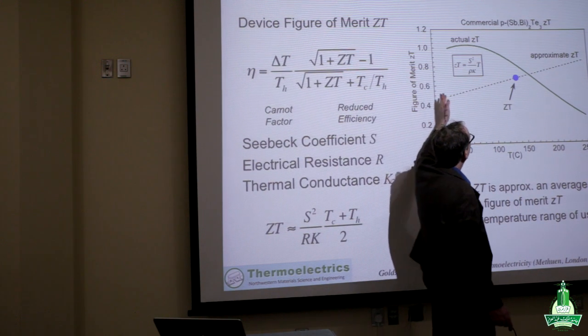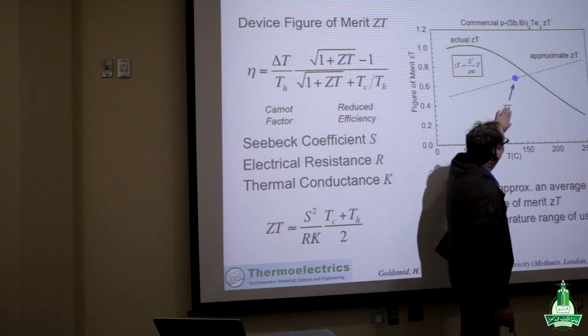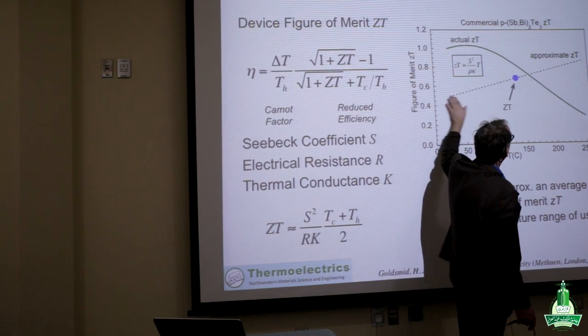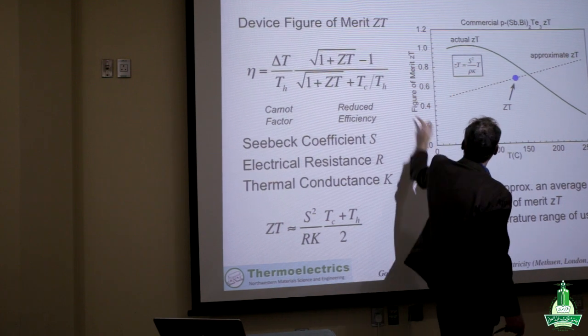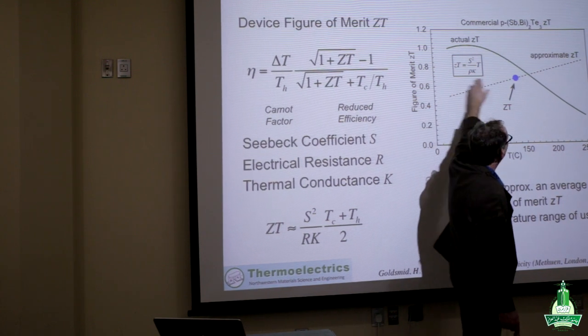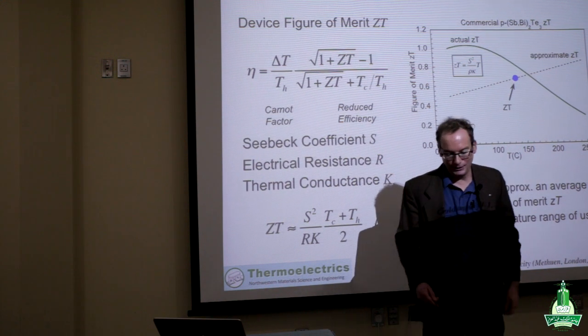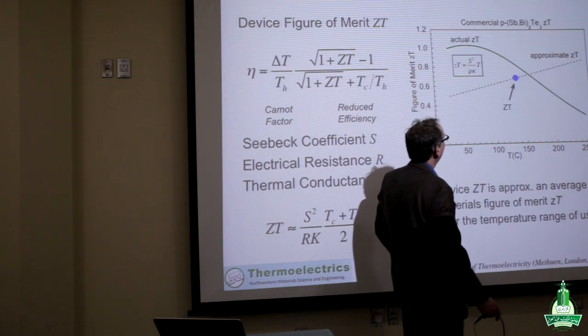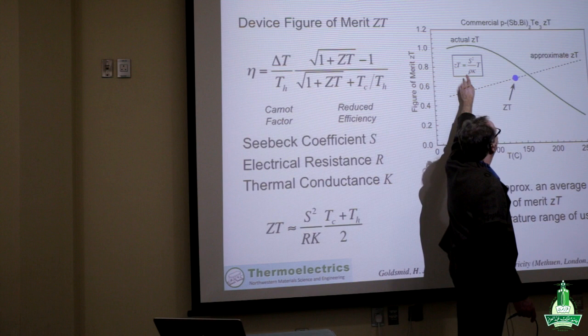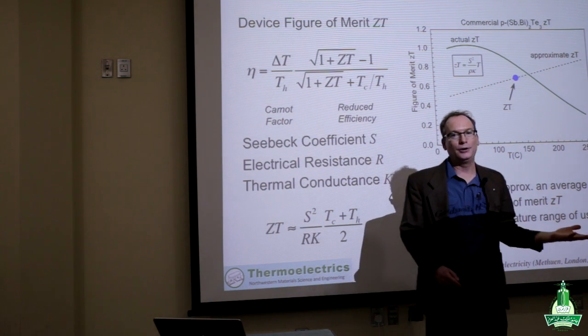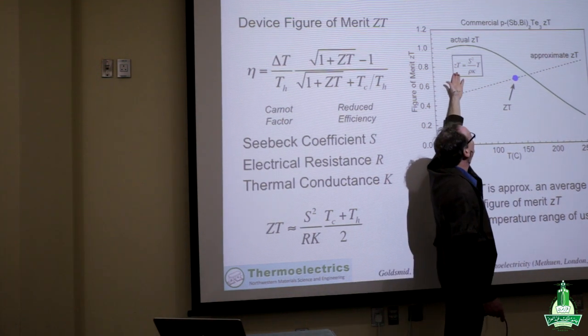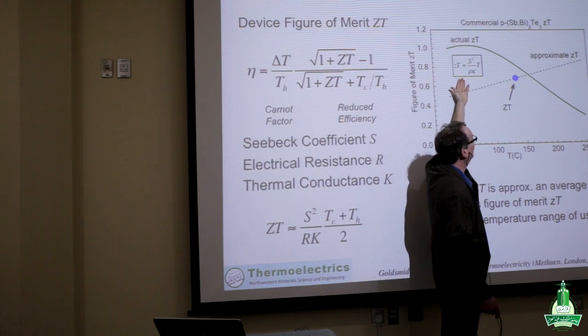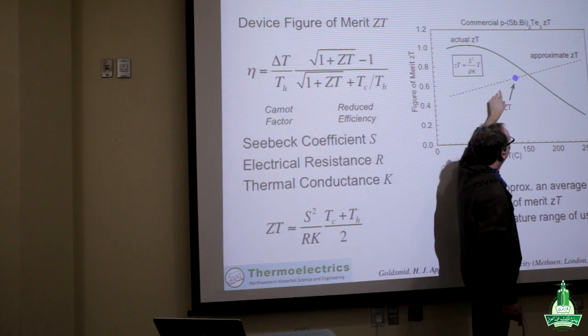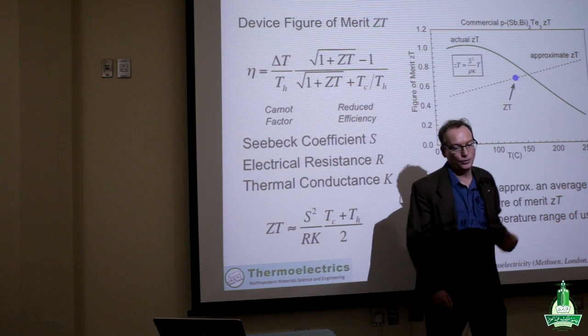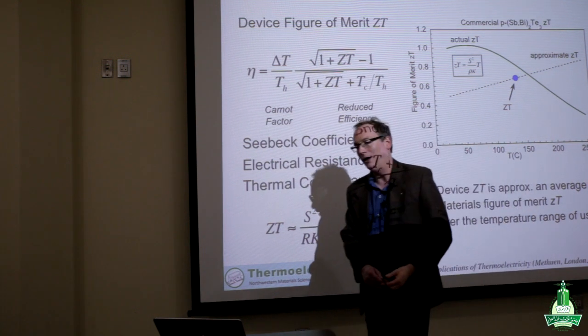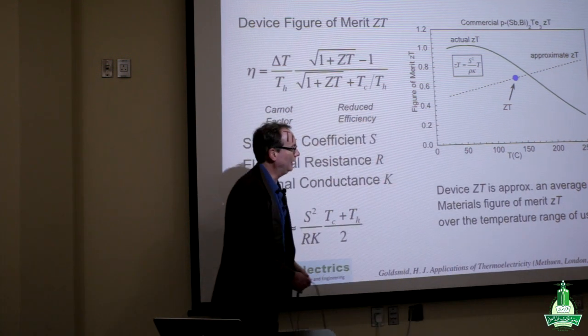Now, approximately the device ZT is an average of our ZT as a function of temperature, but even that approximation is also just an approximation. But we need to keep that in mind when you're reading a thermoelectric paper and they say we have a peak ZT value of 2.6 or whatever. It doesn't mean that the average ZT or the effective device ZT will be that high. Typically, it's just an average.